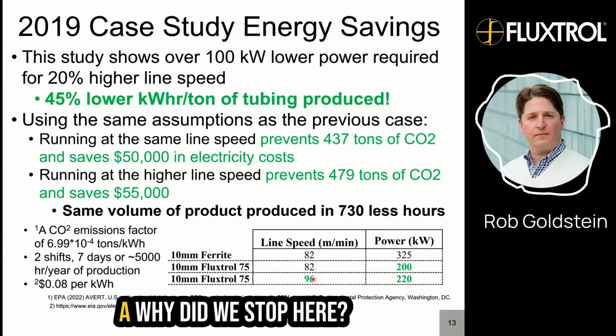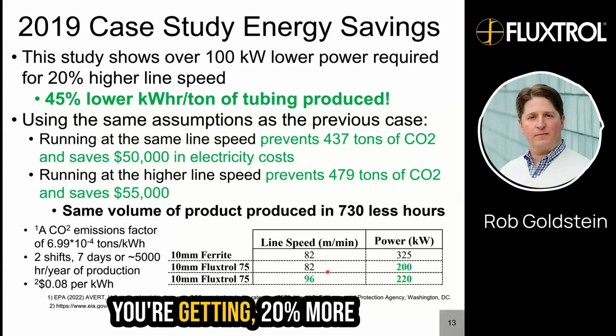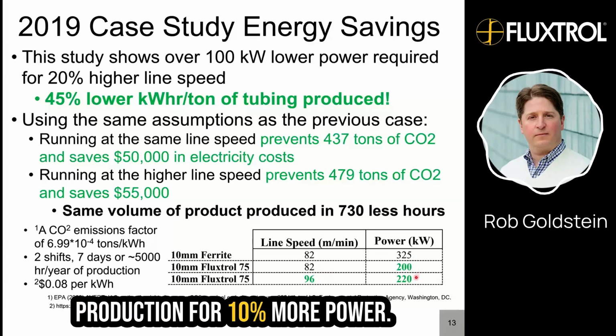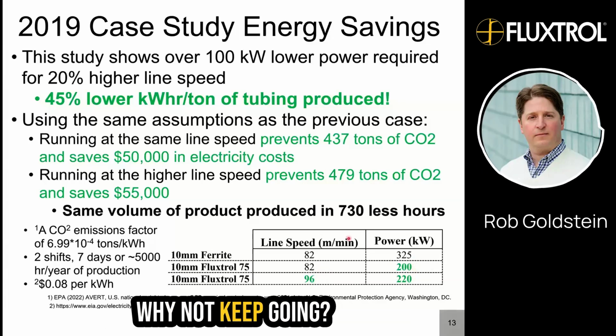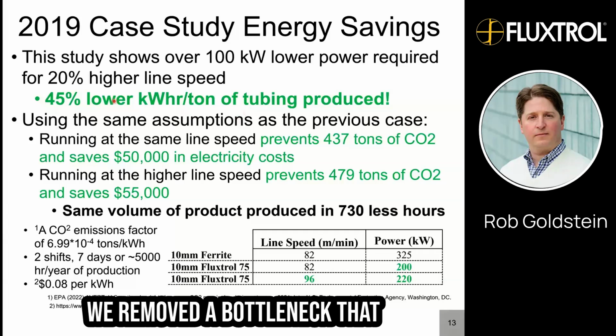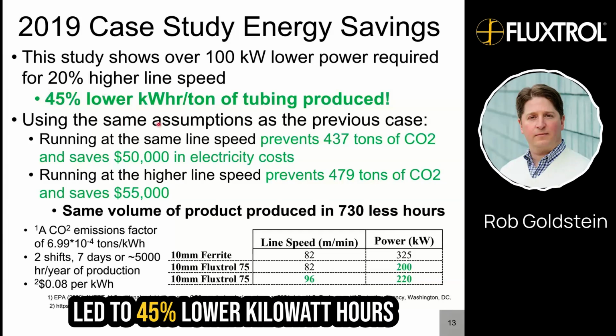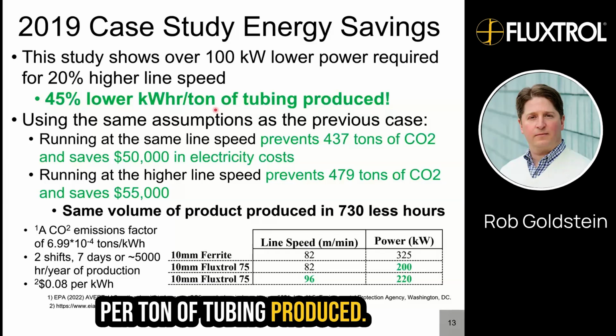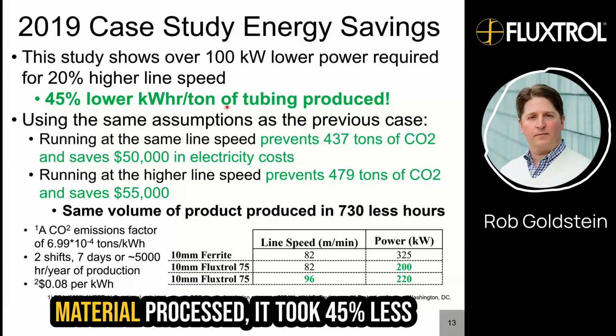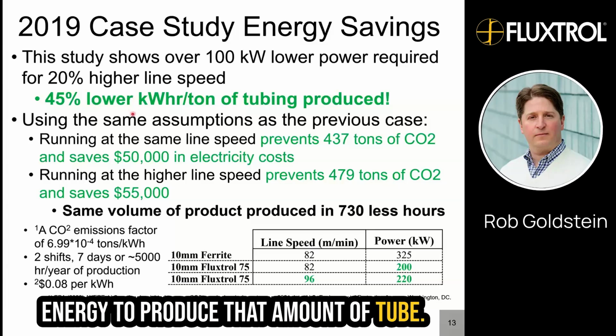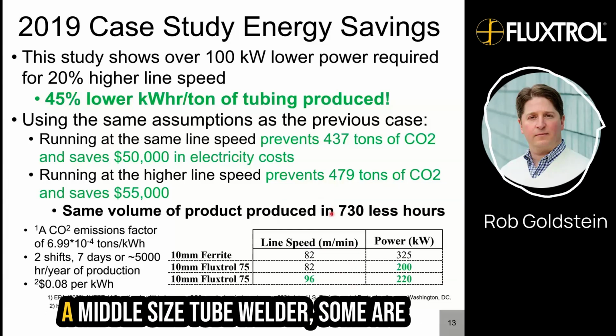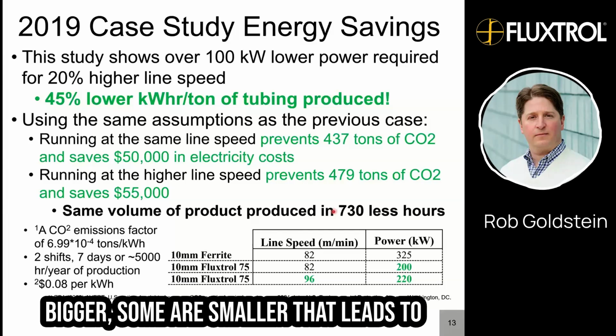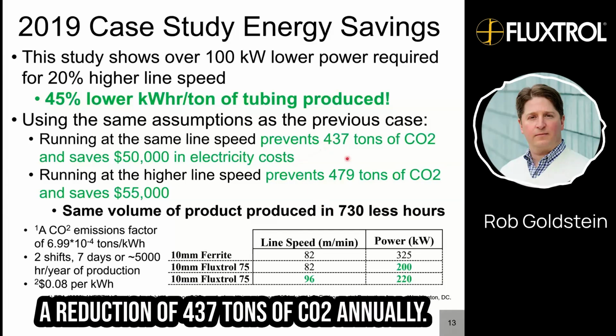So why do we stop here? You're getting 20% more production for 10% more power. Why not keep going? The line couldn't go any faster. We removed a bottleneck. That led to 45% lower kilowatt hours per ton of tubing produced. That means for the same amount of material processed, it took 45% less energy to produce that amount of tube. With these type of powers, and this is a middle-sized tube welder, some are bigger, some are smaller, that leads to a reduction of 437 tons of CO2 annually.